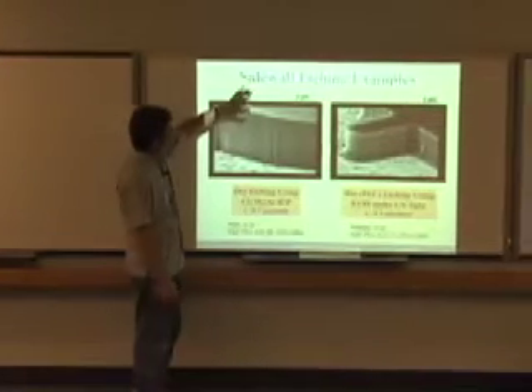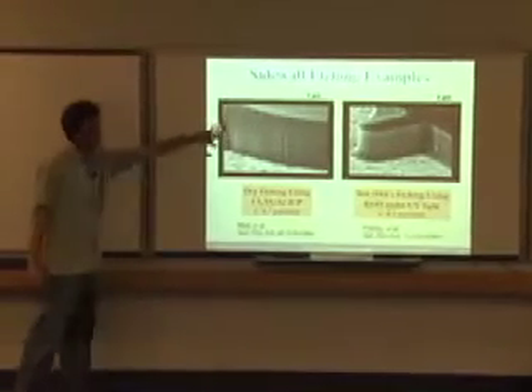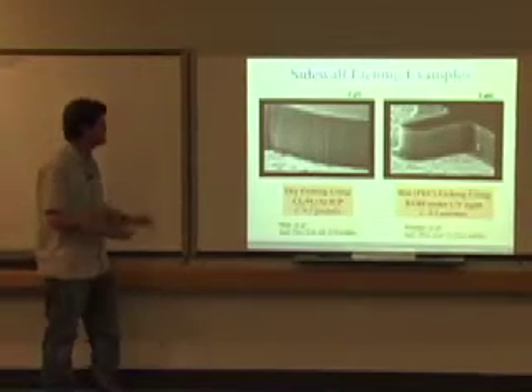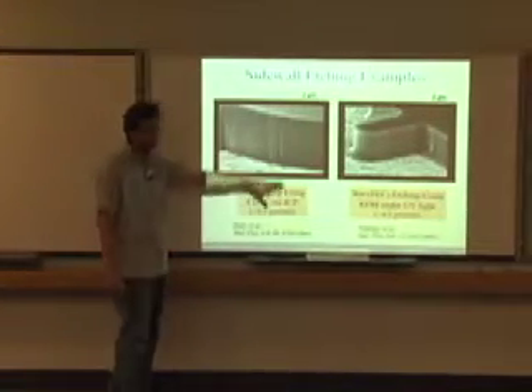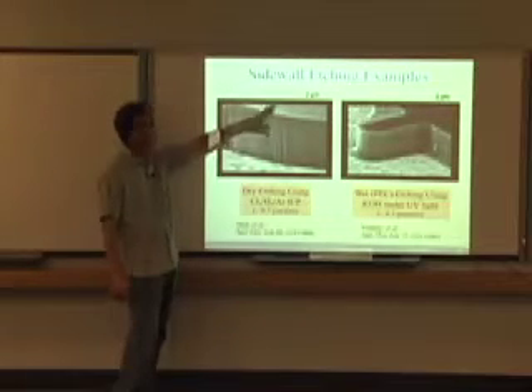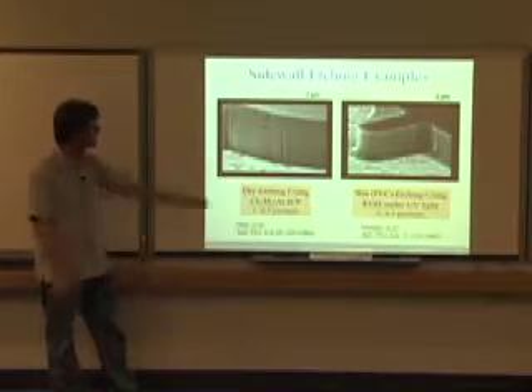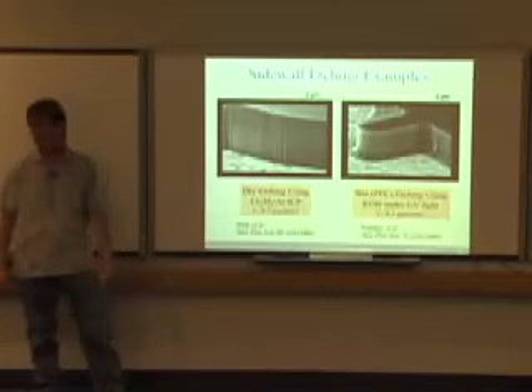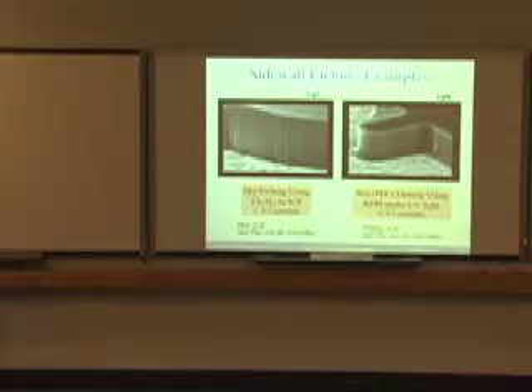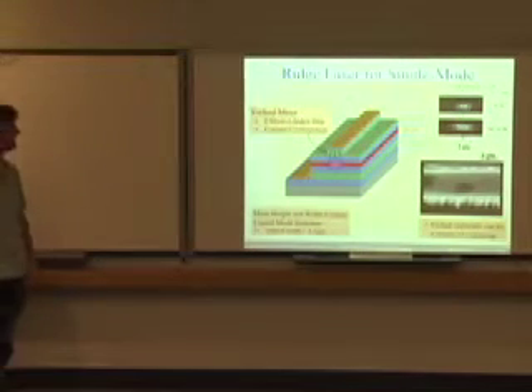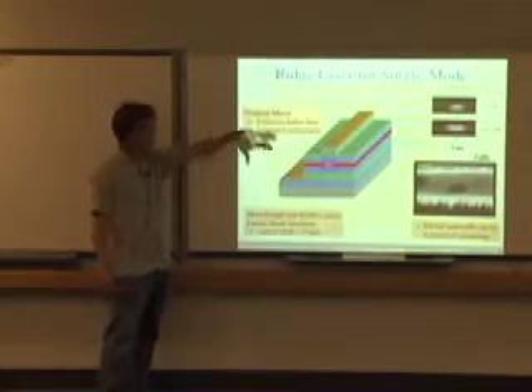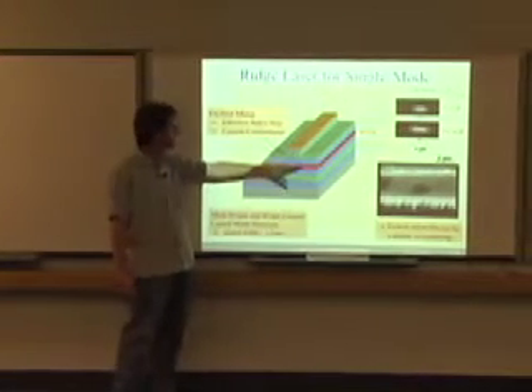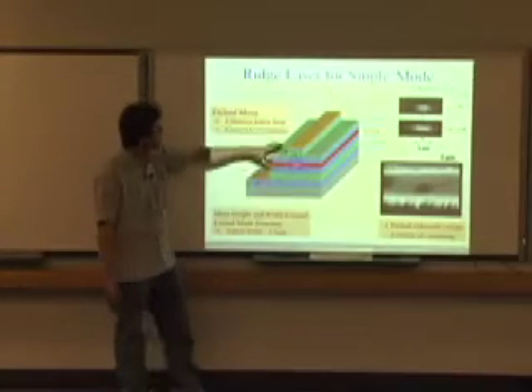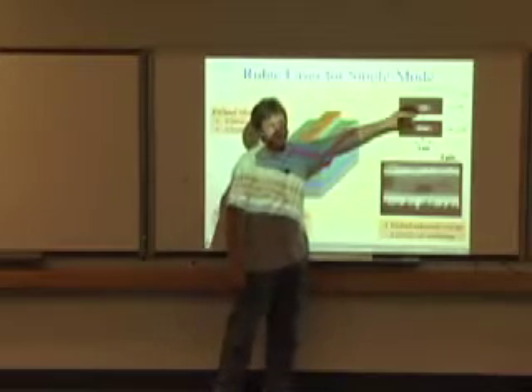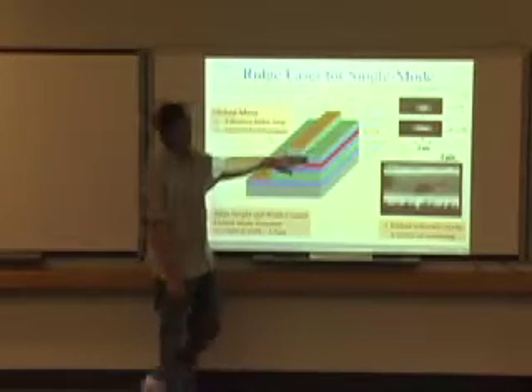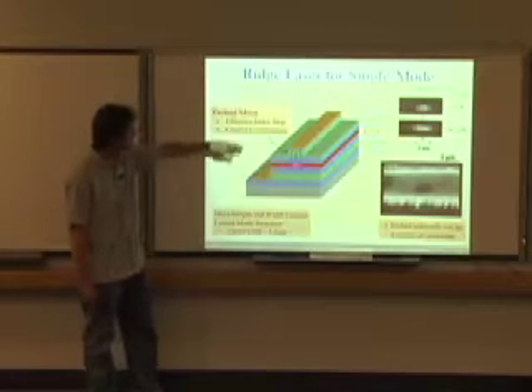But, anyway, so sidewall etching was another thing that was kind of challenging. The material is much stronger, so people developed ways. It's actually fairly standard methods, but it was slower etching, so getting etch selectivities was a bit challenging. I think these days it's pretty routine. But nevertheless, even at that time, people were able to get pretty nice sidewalls in gallium nitride. And I mentioned before the ridge laser's advantage because you could get good current confinement as well as optical confinement. But Nakamura optimized the structure so you could actually get 70 milliwatts single mode behavior from one of these ridge structures. So very nice single mode behavior.